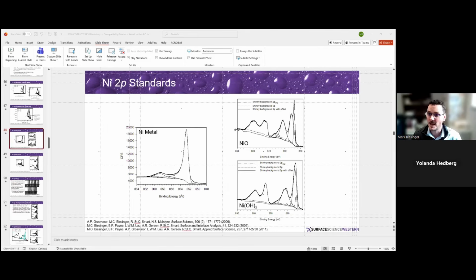The one thing you need to watch for is that sometimes your bulk standards are not the same as what you're seeing on the surface. This is a problem we've seen in the database as well. One example would be the PHI handbook. If I look up cobalt in the PHI handbook, they have a nice spectrum of what they say is cobalt(II) oxide, but they show a spectrum of Co3O4. Their bulk was cobalt oxide, but the surface was not, and we've shown that through work that we've done, which required very carefully controlled analyses. So what you see from bulk analysis by XRD or other techniques will not be what you have at the surface. You have to think about what's going on at those surfaces.